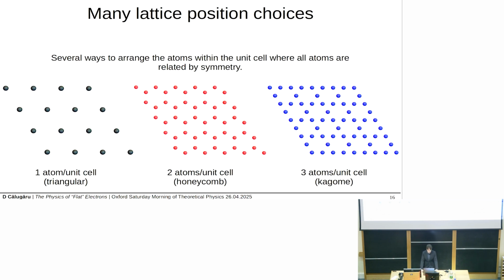The key is that in all of these cases, the atoms really are placed in ways that respect the space group symmetry of the lattice. But the specific arrangement, what we call the Wyckoff position, will determine how the orbitals transform under the symmetry, and therefore how the bands connect in momentum space. So any theory of elementary band representations has to take this into account. You don't just need the lattice and the orbitals, you need to know where these orbitals sit.